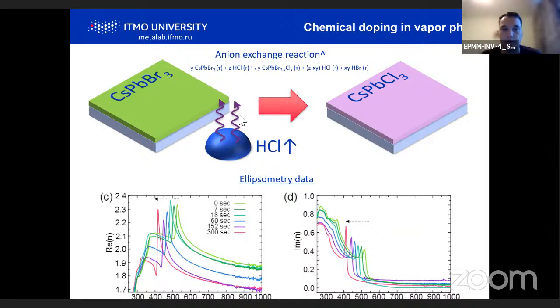So perovskites is a very interesting material because we can provide a very simple reaction like anion exchange reaction, even for thin film. So you see here, if we take a bromide perovskite, then put some HCl acid just nearby, and then wait for some time, we can provide some doping from vapors of this acid, and we can completely replace bromide by chloride. And it results in dramatic change of band gap. So we see here ellipsometry data that refractive index changes quite a lot during the doping just after several minutes. And we see that excitonic properties are still preserved, which is very important for excitonic applications.